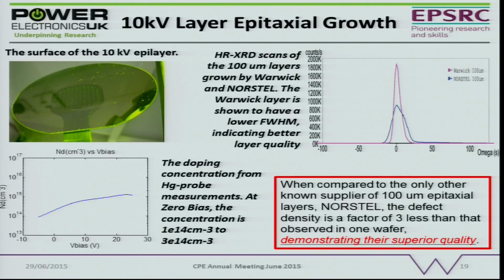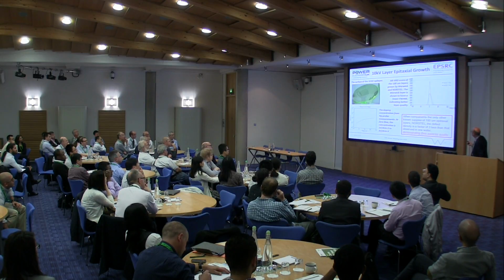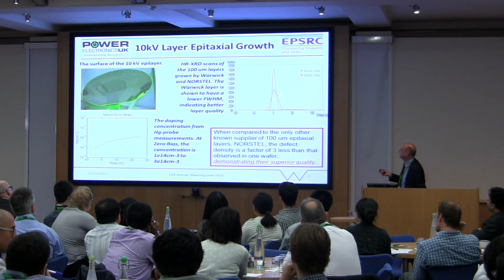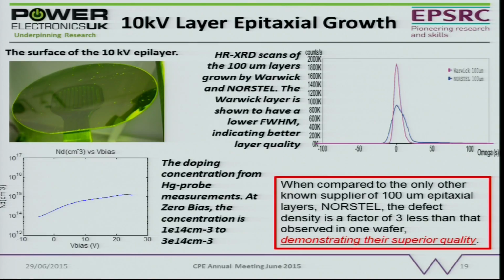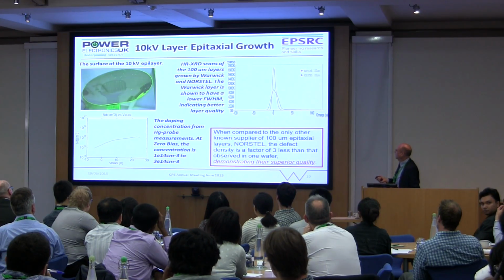And it's very difficult to compare qualities of wafers. So we tried to compare it with other suppliers. Now, I really shouldn't have put the name of the supplier on here, but we have. And you can see that the purple one is our measurement of the epi layer we grew, and the blue one is from another company. And basically, the narrower this peak is, the better the quality of the material is. So we think we're doing a good job compared with commercial suppliers out there. And it's very difficult to get commercial suppliers who give you 100 microns of epi as well. This was probably one of the only ones you can easily go to and get those thick epi layers.